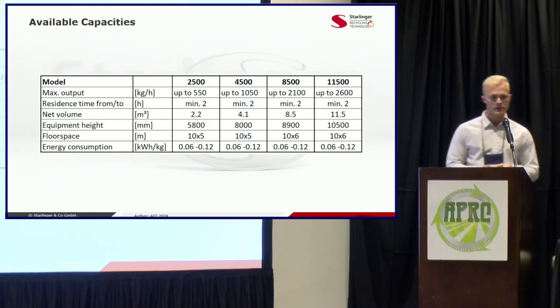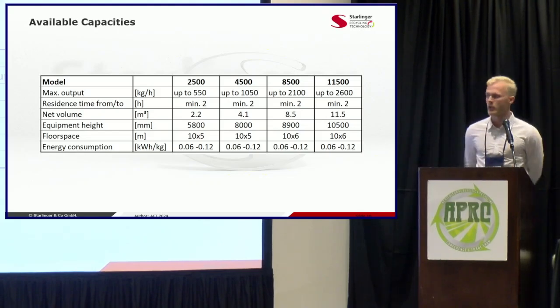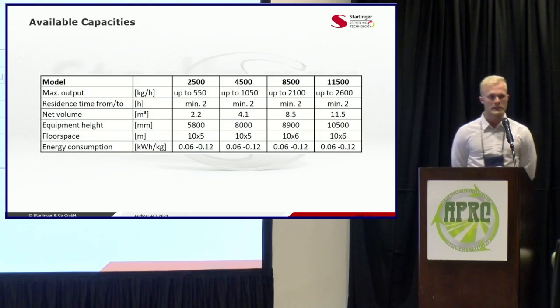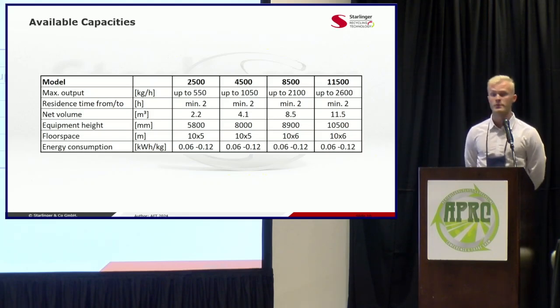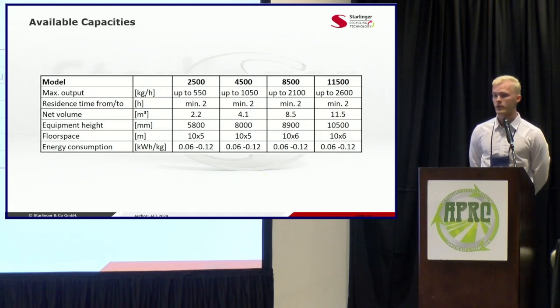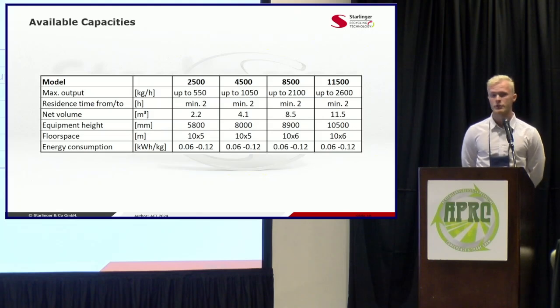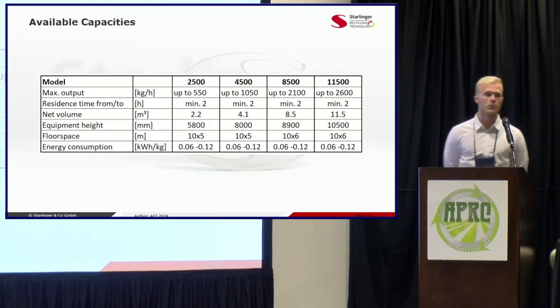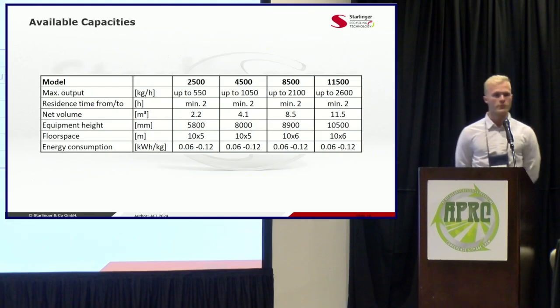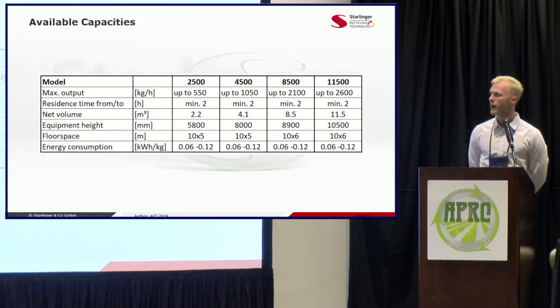So here's the list of capacities for the PCU Plus. Another important thing to touch on is that this is a fully Starlinger produced and Starlinger designed unit. So there are others on the market who of course use different technology, but ours is the most efficient with the lowest residence times as well. So for flexibles, we're looking at about 2 to 2.5 hours of residence time. And for rigid plastics, it's typically in the range of 4 to 5.